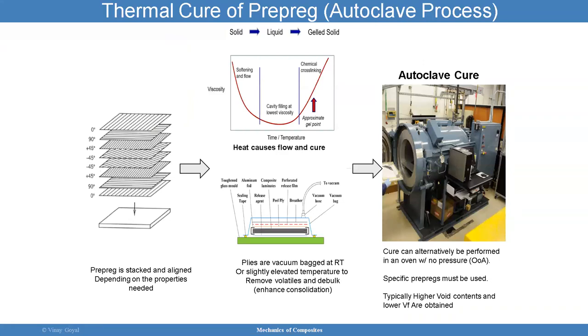So here I have a thermal cure of prepreg. Somebody was asking, what is 45 versus minus 45? Well, you can see here clearly that if I have two plies of 45, they'll be in the same direction. But clearly minus 45 means that it goes in the opposite direction. So it's measured against a particular axis, the layup axis, and all the plies need to be relative to that. So when I say I have plus minus 45, the difference is that one set of plies will follow the 45, and the other set of plies will follow the minus 45. And those two could be different. You can see that they're clearly different in this plot.